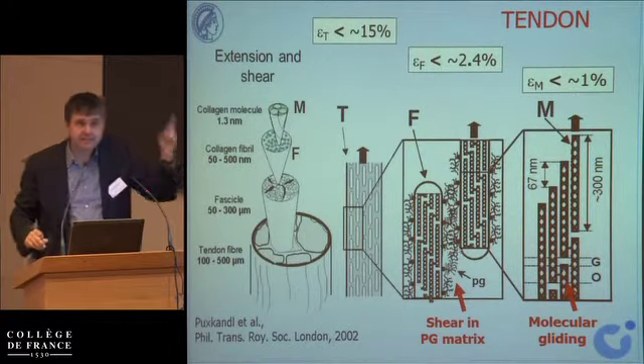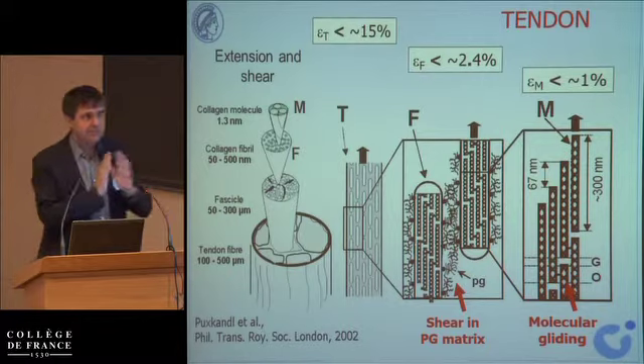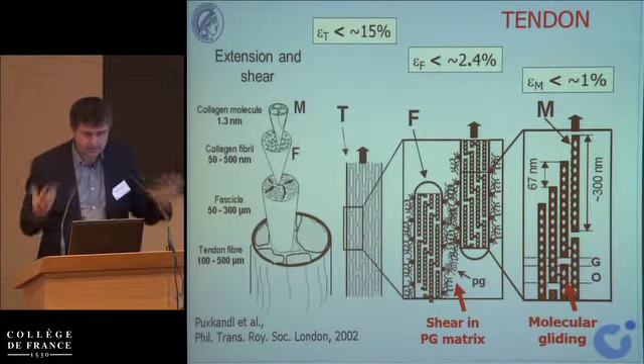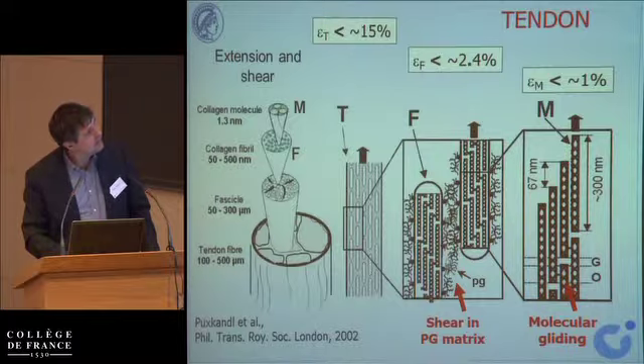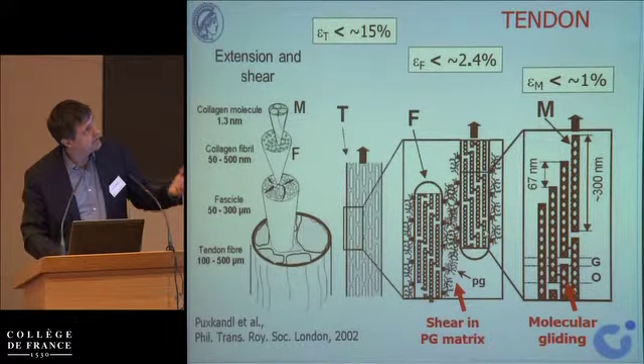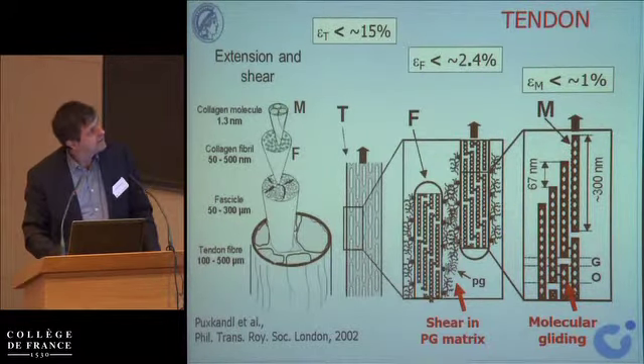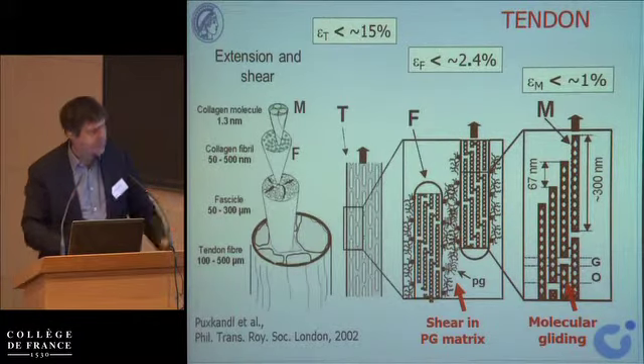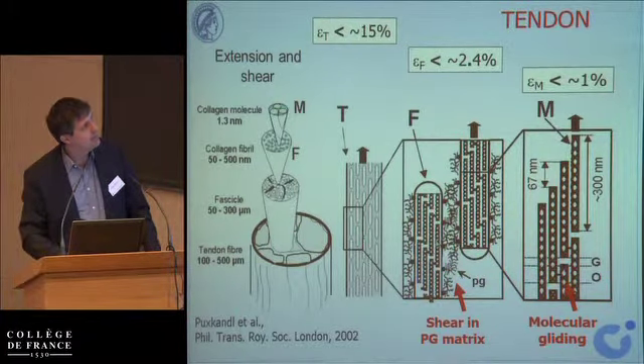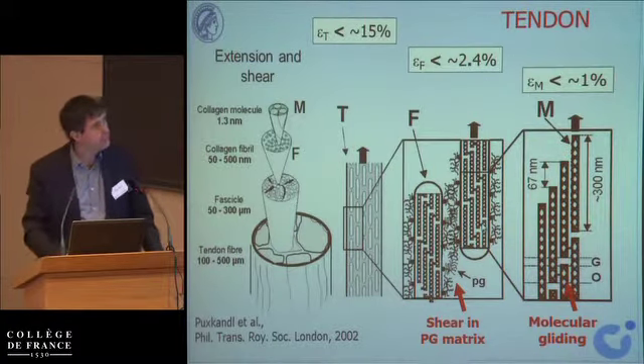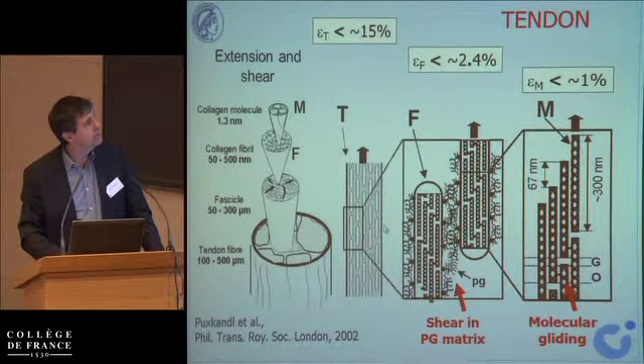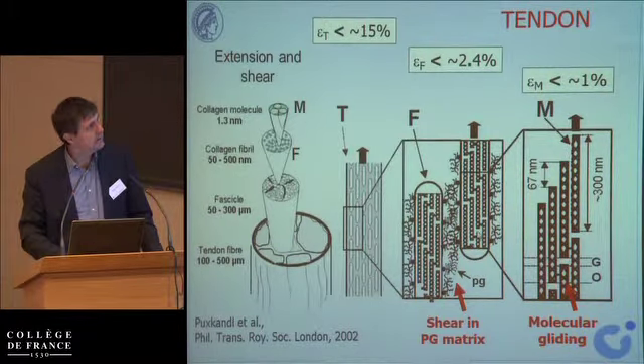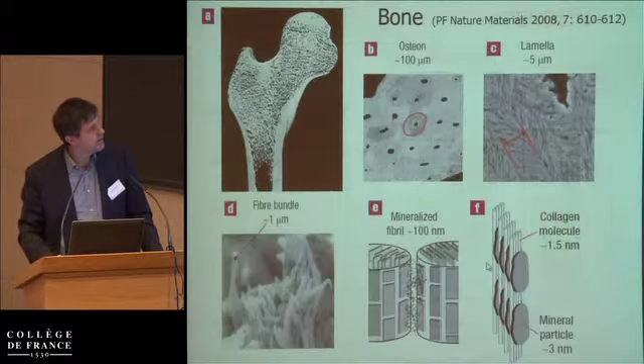So here is another very interesting effect of subdividing materials into a tessellation, because now the surface between the tesserae, or in this case the fibers, allows you shear and therefore a much larger deformation than the individual fiber. This is actually a fantastic way of tuning the stress-strain curve of a macroscopic material by just adapting these values by the right materials down here, the crosslinks and so on. So you can actually design the shape of a stress-strain curve in this way.